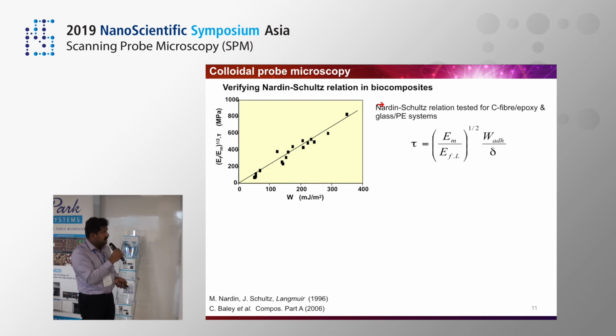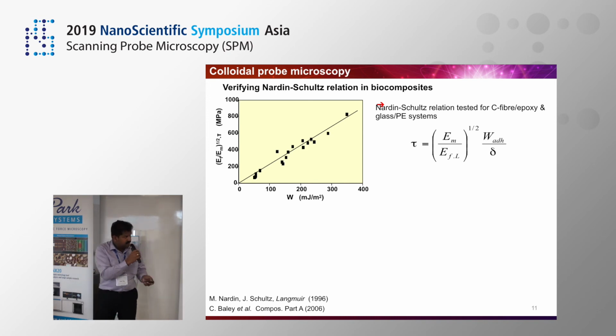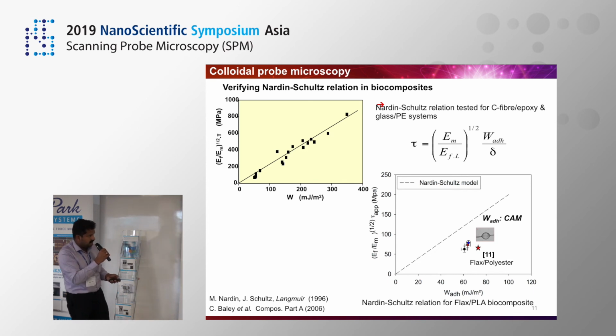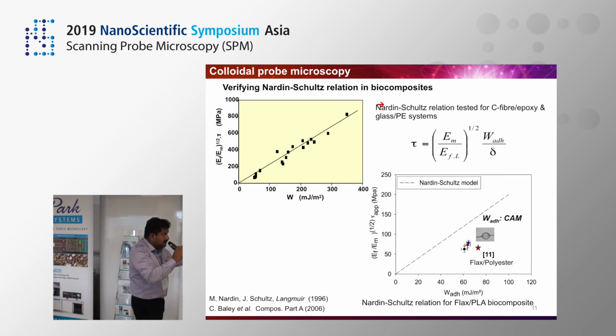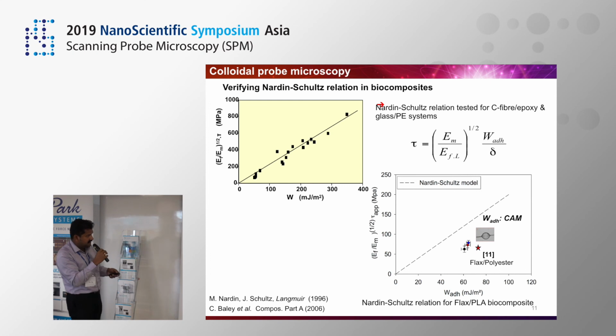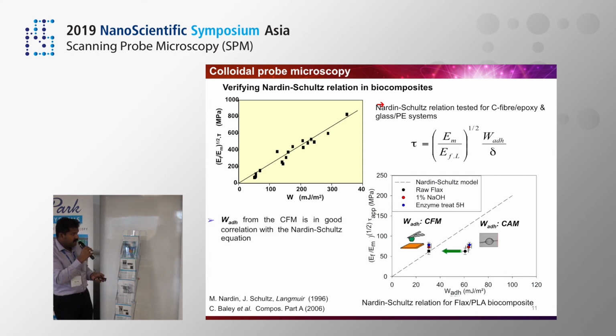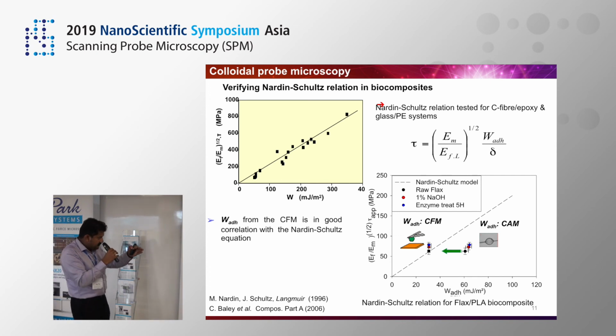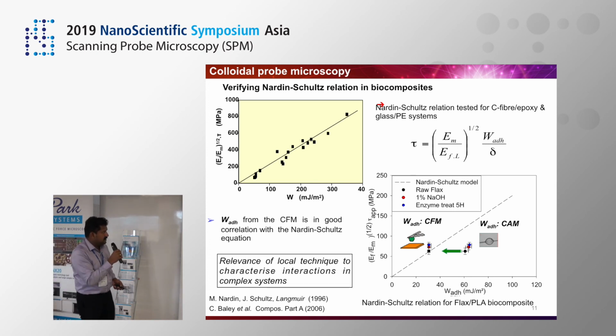The practical significance of the results is here. This is the Nardin-Schultz relation that relates the work of adhesion to the interfacial shear stress between the matrix and the fiber. For materials like carbon fiber epoxy and glass polyester systems, we have a linear relation between the work of adhesion and interfacial shear stress between the fiber and the matrix. However, that relation is not exactly true when we take work of adhesion from contact angle measurements, for example, contact angle of PLA over this fiber, because this is a bulk technique, we have this deviation from the linear relation. However, when we use the work of adhesion from the colloidal probe technique, which is a more local technique, that gives a better agreement with the Nardin-Schultz relation. So here we show the relevance of these local techniques to characterize interactions in complex systems.